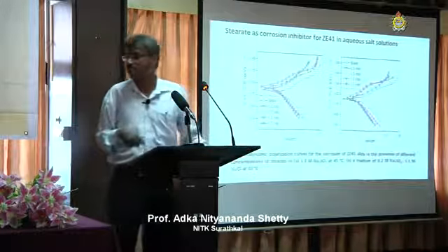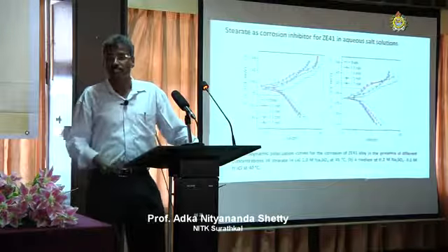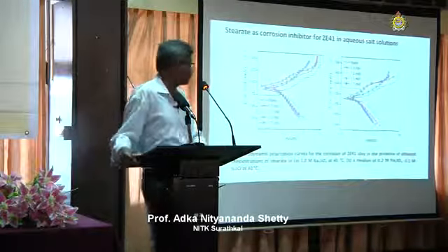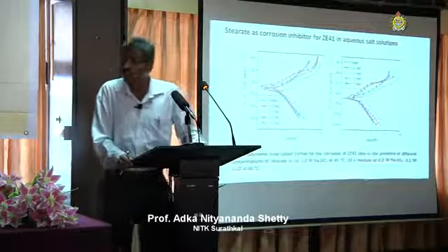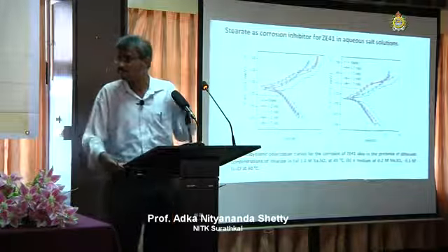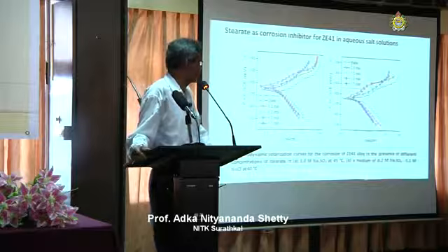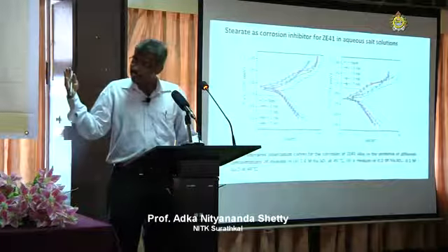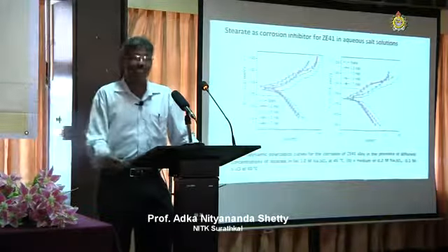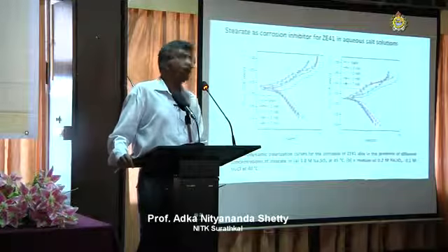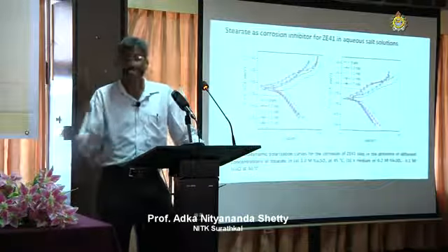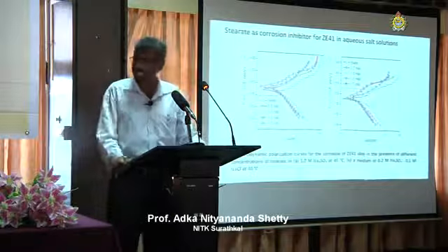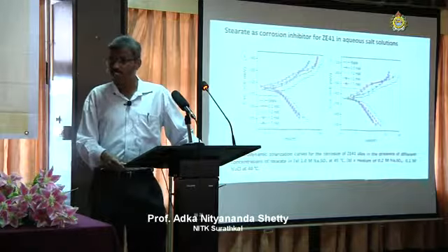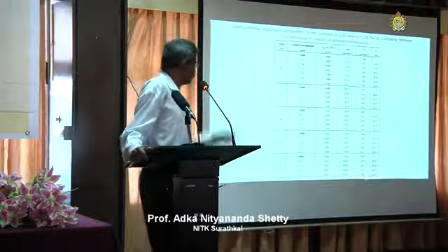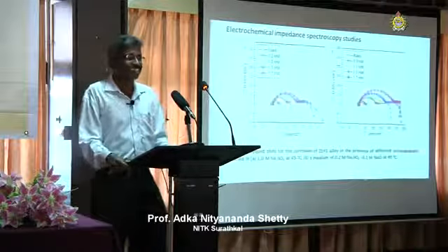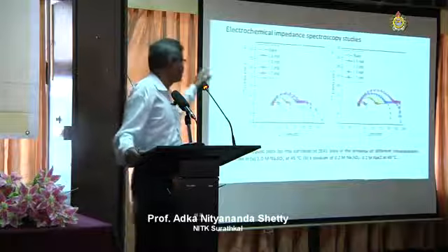For those who have carried out the experiment with potentiodynamic polarization measurements, by looking at the plots you can make out that as the concentration of the inhibitor increases, the plots are shifted towards lower current density regions, indicating that the corrosion rate decreases with the increase in inhibitor concentration. Next please. These are some of the values that can be skipped. I thought if there is sufficient time I could have shown all these things.